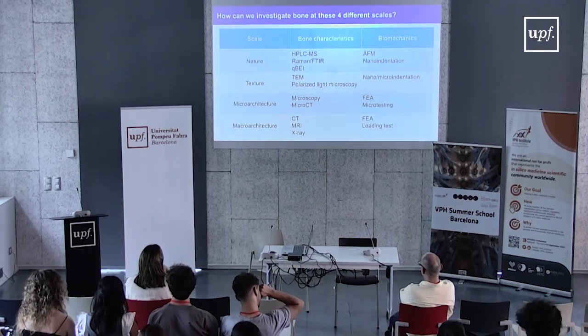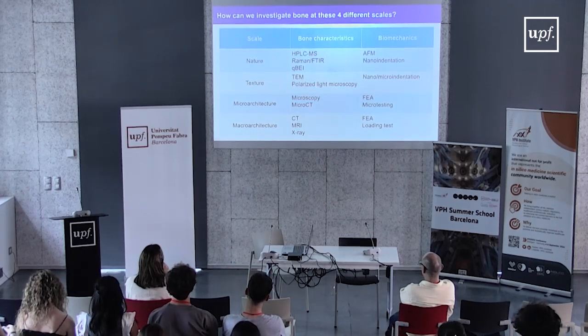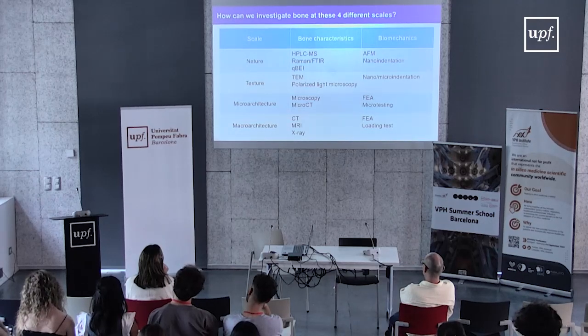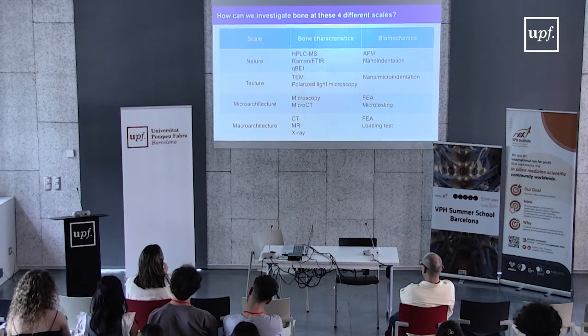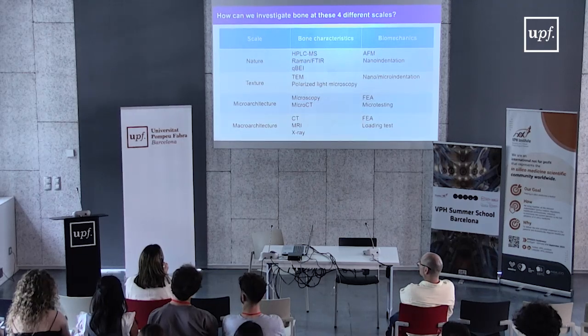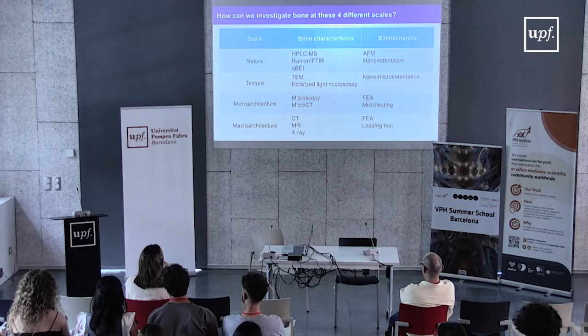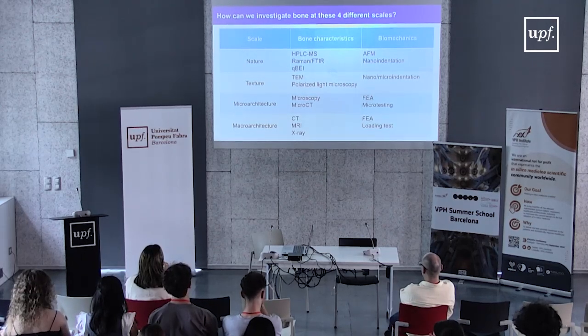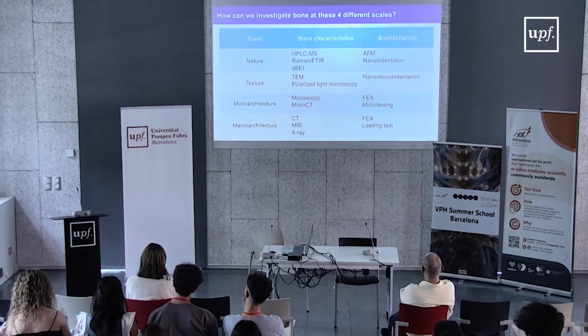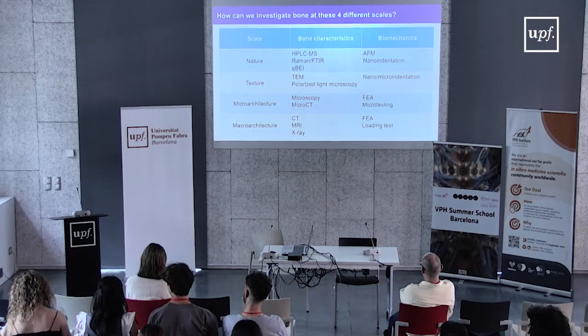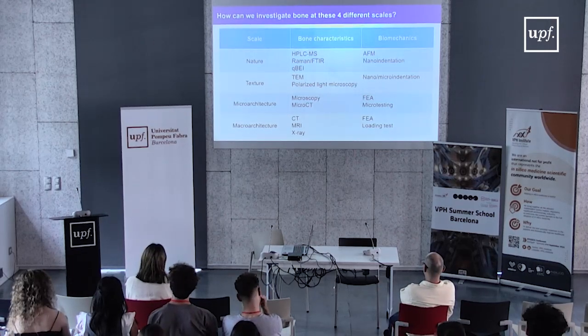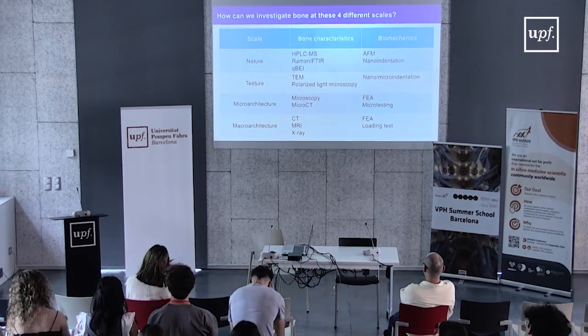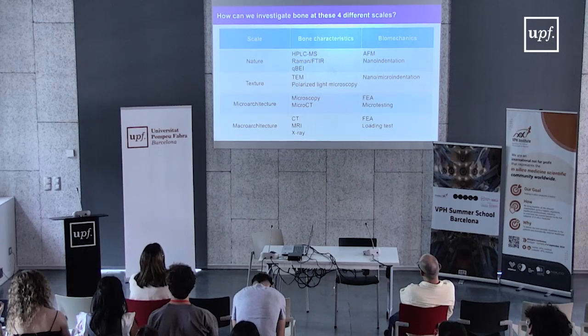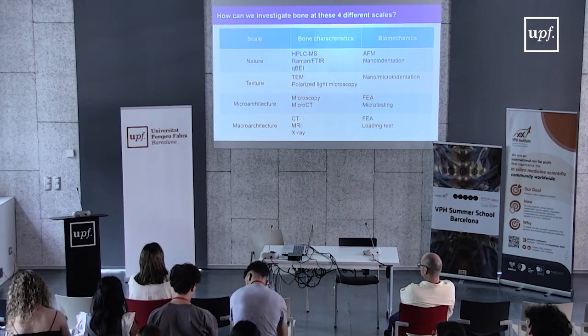If it's at the scale of the texture that we want to look at the bone characteristic, we can do TEM, electron microscopy, or use polarized light microscopy to see if we have this pattern of bright and dark line. And again, in terms of biomechanics, we can perform nanoindentation or microindentation. If now it's at the level of the microarchitecture that we're interested, we can do micro-CT or microscopy in 2D. And we can apply finite element analysis or microtesting to measure the ground truth of biomechanics of the bone structure and to have an idea if there is a fragility or not. And finally, if it's at the macroarchitecture, we can use CT scan, MRI, or X-ray to determine the geometry and the shape of the bone pieces, and we can still apply FEA or loading test to have the ground truth and measure if there is a default in strength and response of the bone.